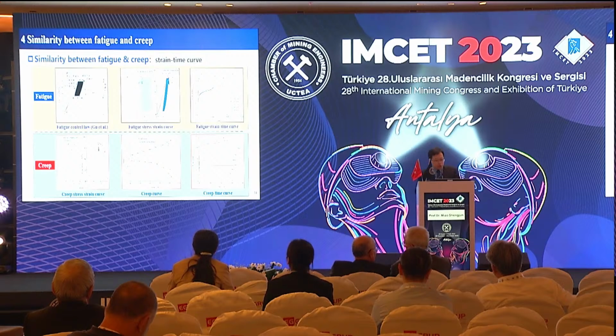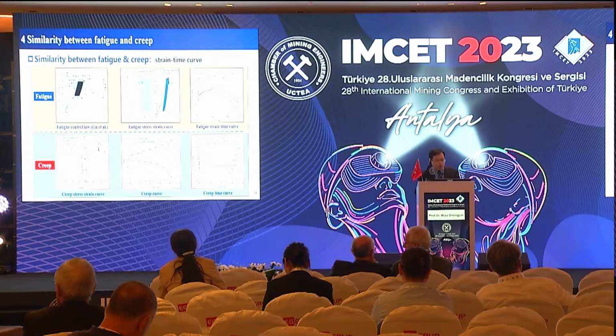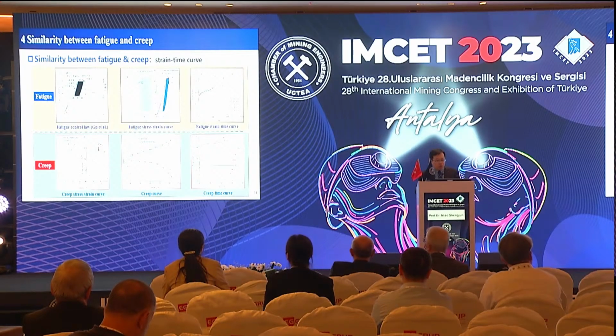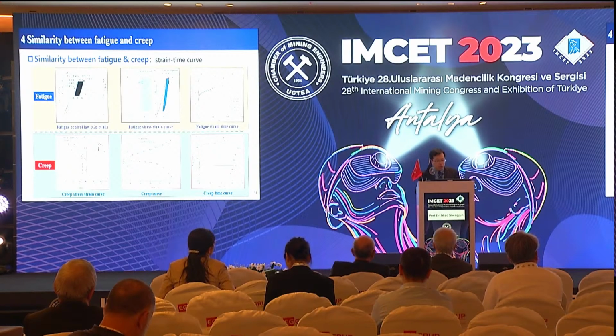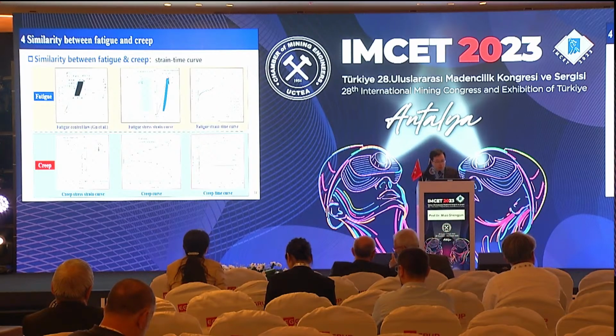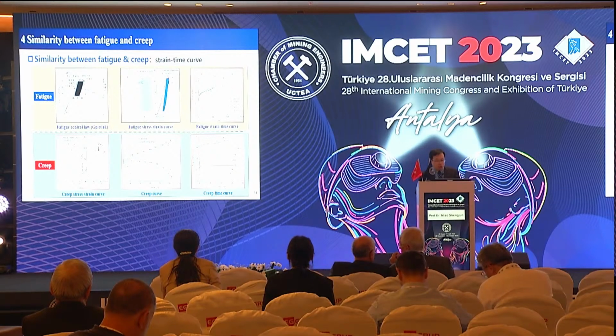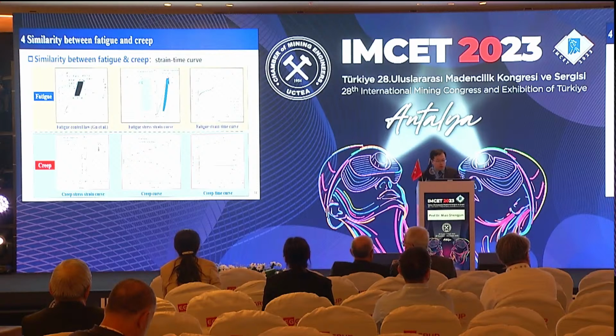As early as 20 years ago, Chinese expert Xu Renge and former president of the International Society for Rock Mechanics, Ian Brown, found that the deformation behavior of rock under cyclic loading is controlled by the stress-strain curve of monotonic loading. In addition, both the fatigue deformation curve and creep curve of rocks show typical three-stage characteristics. Therefore, we used rheological theory to study the fatigue failure limit of rock.